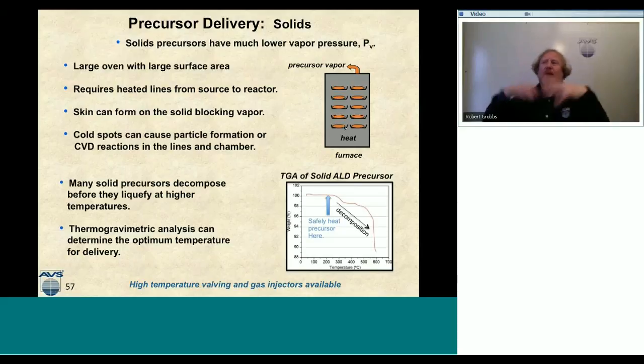So you heat it, and then sometimes the vapor pressure just starts to turn off, and it's because you've made this skin on top of the solid. So sometimes you have to chip away at it to get it to go again, and to start producing precursor vapor. So solids are pretty tricky to deliver. They can be delivered, but they're tricky, and it depends on the particular compound or material you're trying to grow, depending on how much trouble you're going to have doing that.